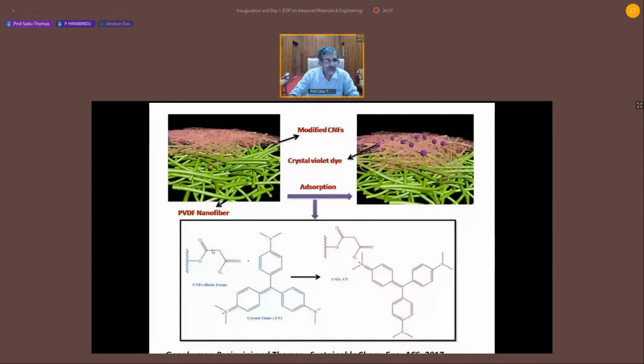You can see this is our nanocellulose, which is chemically modified. I will show you a small chemistry we have done. My PhD student did a small chemistry. You see, this is our nanocellulose, which is chemically modified with maleic acid. So we have COO minus group on the surface. This is the dye from the textile industry. And this dye can form some sort of electrostatic interaction. And you see, this is our filter we have designed. When we put this water to our filter, to our beautiful filter, you see all the dye particles are being removed. And the reason is because these dyes can form an electrostatic interaction with the nanocellulose.